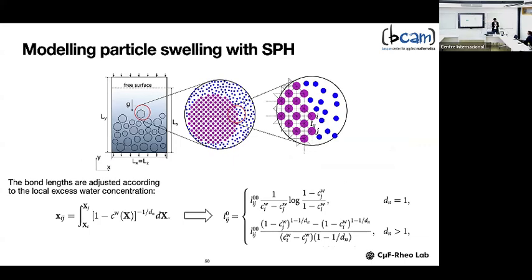They are linked with springs. They have a kind of equilibrium length. Now this equilibrium length depends on the amount of water contained inside the liquid, and therefore we solve this equation analytically, and we end up with an expression for the equilibrium length, which depends on the concentration of water in particle I and particle J. The bigger the water concentration, the larger the stretch of each spring forming this particle, and therefore it will produce swelling.